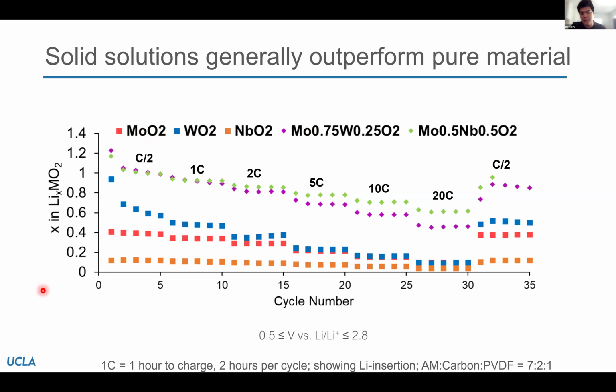What we're looking at here is a charge-discharge plot where on the y-axis we're measuring the capacity, or how much lithium is able to be stored in our material. Each one of these points represents a charge and discharge cycle and how much of that lithium reaction they're able to participate in. And these different C values describe the different charging speeds. So here at C/2, we're looking at a charge in 2 hours and a discharge in 2 hours. 1C is a charge in 1 hour, discharge in 1 hour. 2C is in half an hour, and so on.